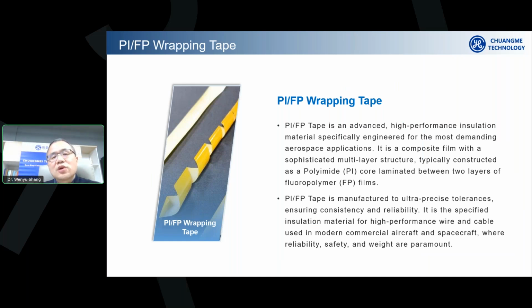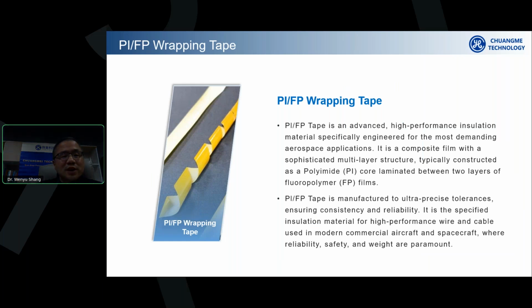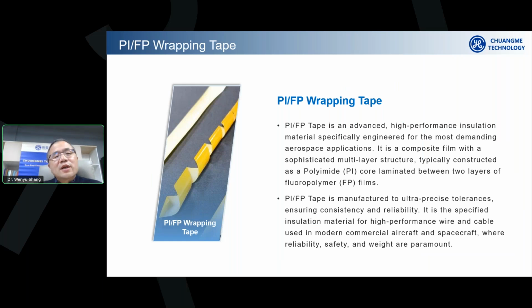After we wrap the whole wire with this wrapping procedure, we put the whole cable through a high temperature oven. Usually the temperature is set at 350 degrees C to 400 degrees C, depending on the machine and the speed of the wire passing through the oven, to fire and solidify the whole wrapping layer into a continuous insulation layer. Okay, because of this firing and solidification procedure, that's why we have this FP layer on the tape.